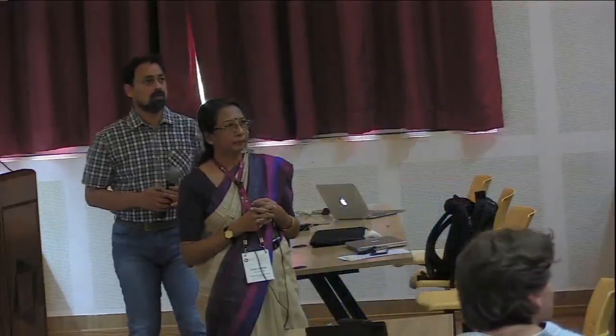Thank you very much for the nice talk. I have one question. In the process where you apply a field in the clay, wouldn't you expect also that there would be electroosmotic flow? Actually, we wait till the gelation goes up to a certain extent. If it is completely liquid, then it's difficult to do the experiment, and there would be electroosmosis and gelation. Sure, but if you have a gel, then the matrix is fixed, but the fluid can still be transported. So I would expect that you have an excess of fluid moving towards the negative electrode and maybe evaporating on that side. So that might explain why the positive side is getting dry more quickly.